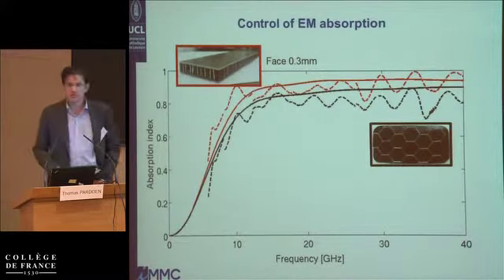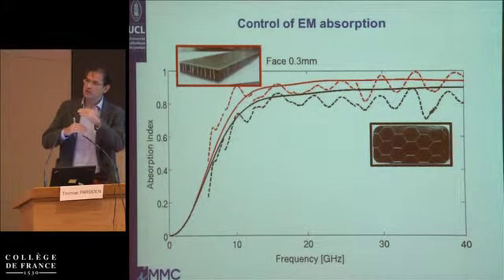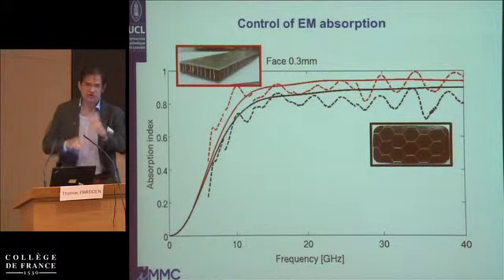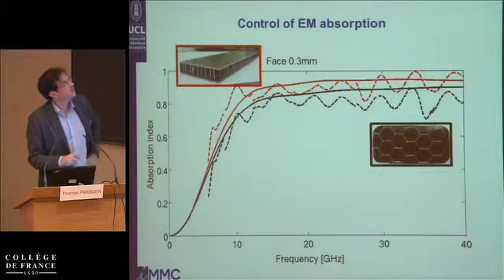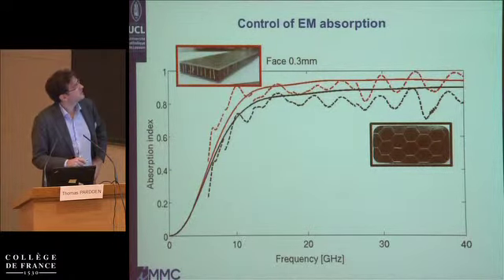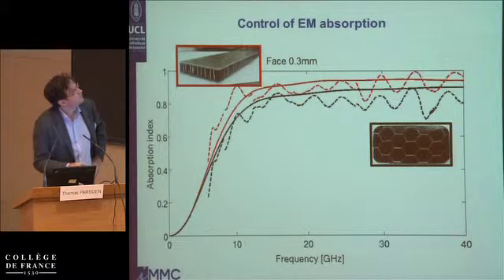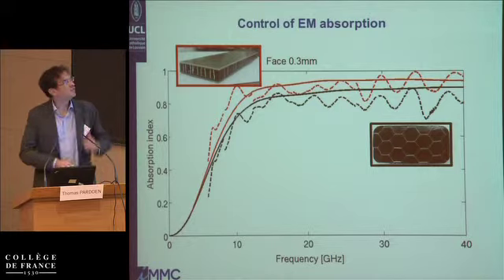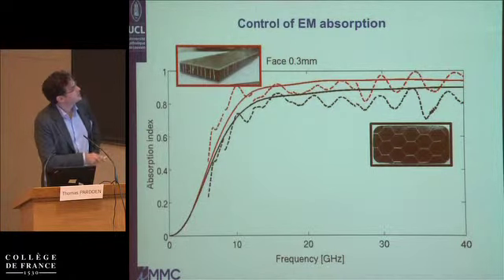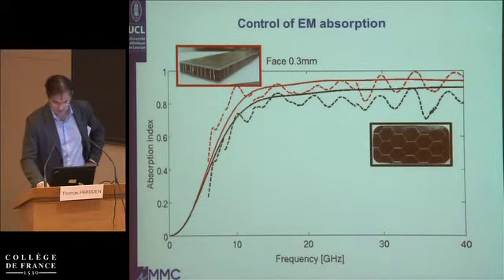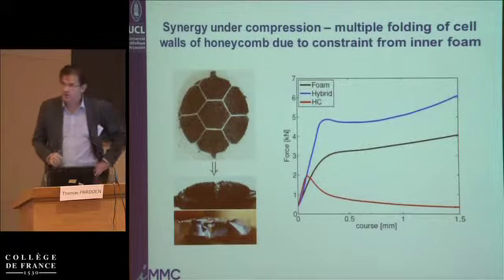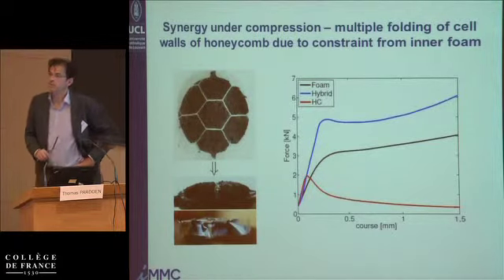The good news is that with the glass fiber composite on top of the material, we're not losing the EMI shielding capacity or absorption capacity. We even improve it a little bit. So black is for just the core, and red is for the core plus the face sheet. This is the absorption index as a function of frequency again. Now the question is, do we get good mechanical properties with this material?